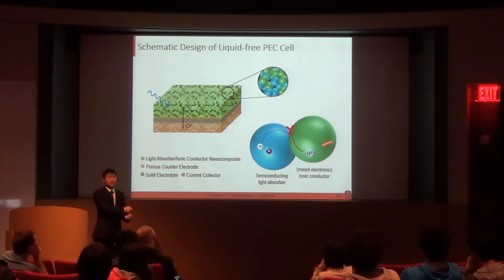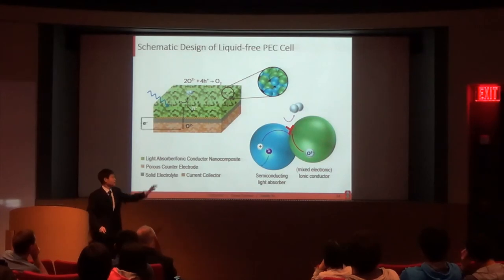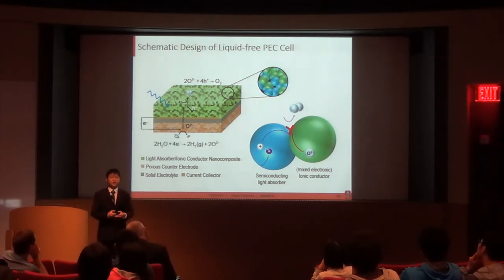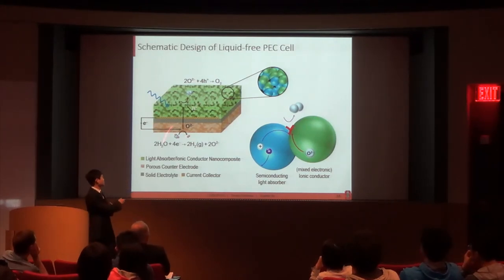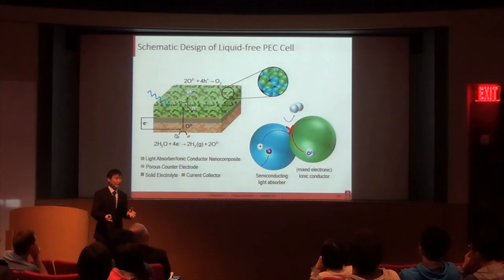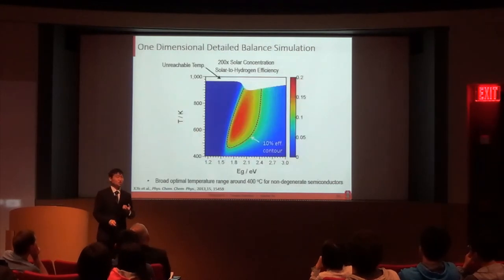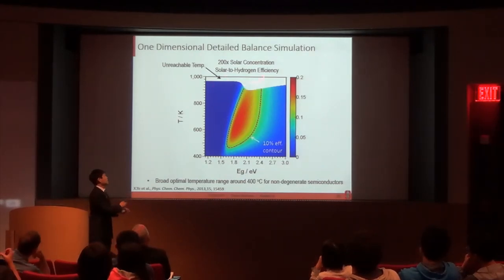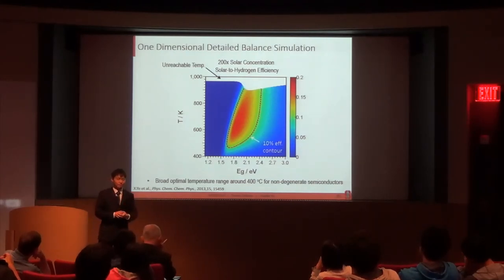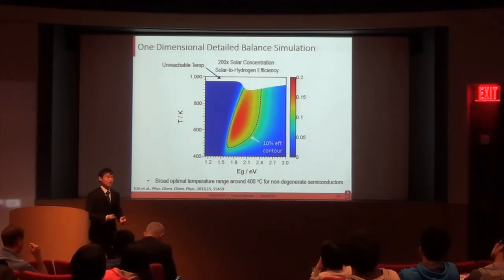So as the hole meets an oxygen ion from the ionic conductor, they can react and release oxygen. And on the other hand, the electrons will be collected by the external circuit and complete the reaction on the counter electrode. So I have carried out a complete simulation on this kind of geometry based on a one-dimensional detailed balance model. Without going into too much detail, the results show that under 200x solar concentration, a practical efficiency above 10% can actually be achieved within a broad range of temperature around 400 degrees Celsius for a non-degenerate semiconductor. So encouraged by this simulation result, we moved on to realize our idea experimentally.